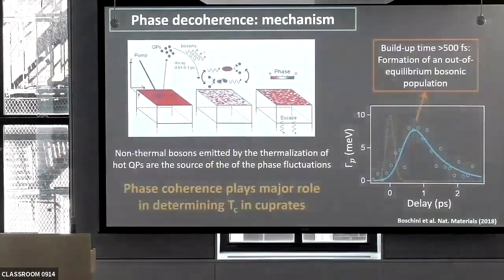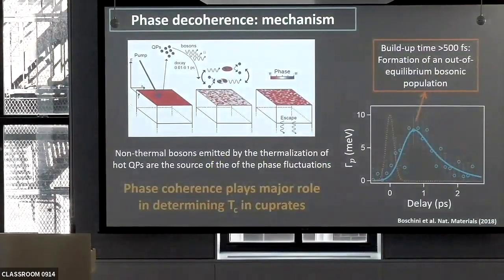So going back now to the model or the interpretation: you're pumping the system, you are creating a population of hot quasiparticles. Those will thermalize by interacting with bosons in your system, and as they do, you're breaking more quasiparticles, so you're scrambling the phase coherence of this condensate, and eventually, as the system relaxes, it goes back to itself. So the conclusion would be, if this is a measure of superconductivity being quenched, it is really driven and controlled by phase coherence, which then confirms the role of phase coherence in the high TC phase diagram, especially the underdoped.